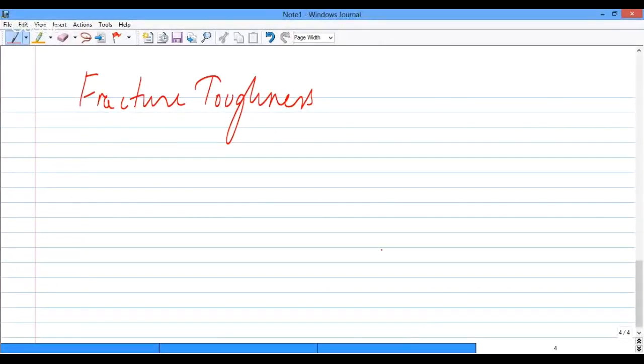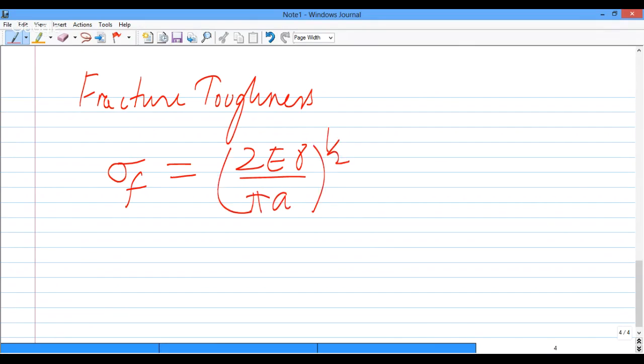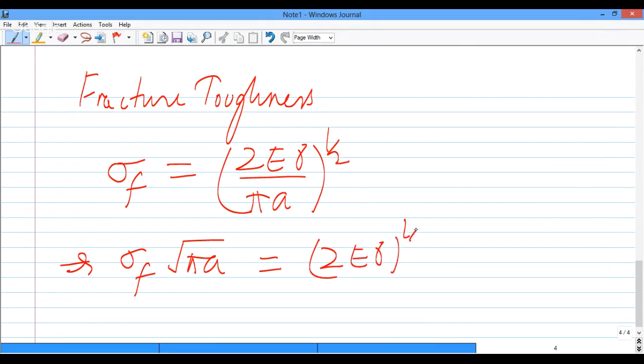There is of course a third kind. These two we have mentioned in the course. There is a third kind of toughness test also, and that is called the fracture toughness. We have not really discussed this in this course, but fracture toughness is related to our Griffith's formula, sigma f = (2Eγ/πa)^(1/2). So if you write it as sigma f square root of πa, then you find that it equals (2Eγ)^(1/2). So this is a material property, and you can define this material property as some sort of fracture toughness. So that is called Kc.